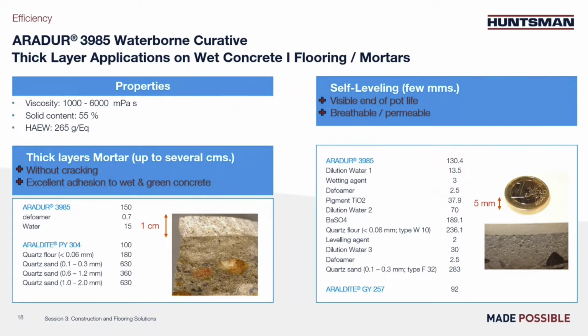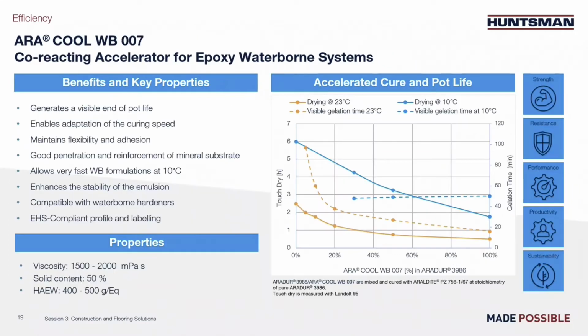So on the right side, it's a self-leveling system. It's about 5 mm thickness. In this case, the resin is Araldite GY257. This resin is not formulated here. The hardener is, with a specific process allowing the good incorporation of all the elements. This self-leveling is breathable, meaning that vapor can go through. You can then avoid blisters in case humidity would come up from the ground. You get a matte appearance, self-leveling with a very good adherence onto the substrate.